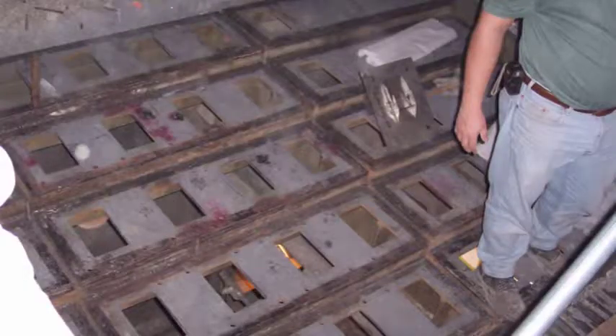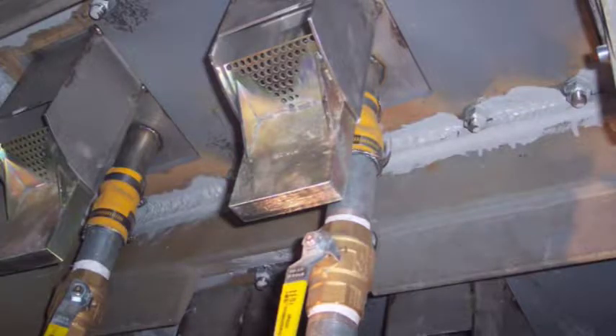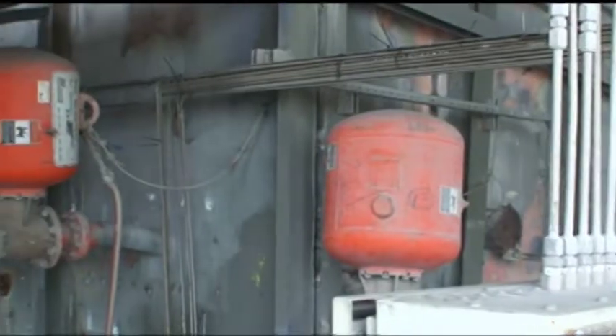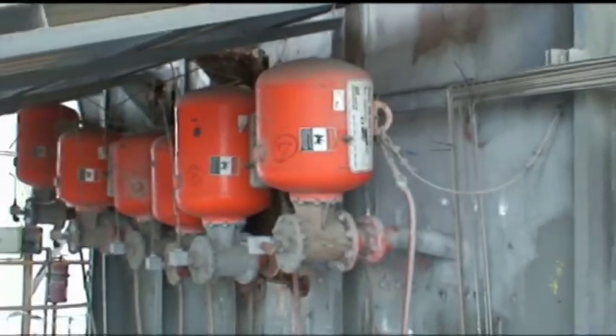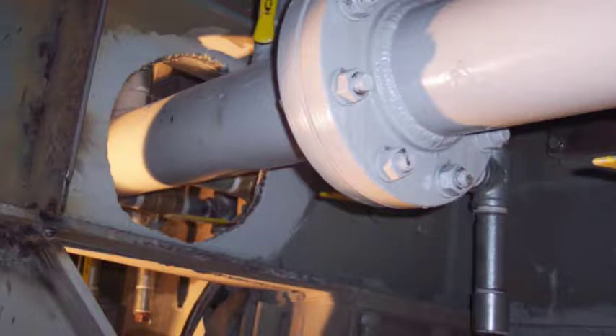In a planned shutdown in March of 2007, designs to address and solve these issues were moved from the stages of planning into action. It was during this shutdown that a grating was introduced that could withstand temperatures up to 1,000 degrees Fahrenheit. Redirection of the blaster airflow distributed throughout the grates brought precise air power where and when needed to the troubled areas of the cooler, where prior snowman formations were virtually unreachable under full production.